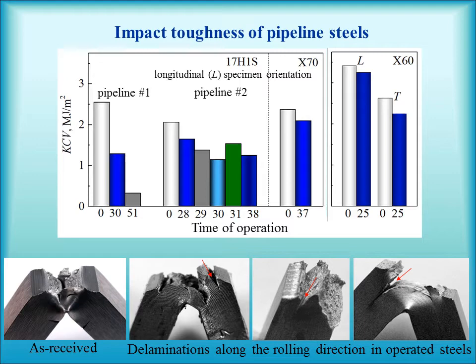It is known that the main characteristic for assessment of pipe steel resistance to brittle fracture is impact toughness. And this parameter decreases with operation time for all tested steels. It also depends noticeably on specimen orientation, as illustrated for the steel X60. Fracture of transverse specimens realizes by detachment along structural elements of the texture and therefore requires less energy consumption. In the case of longitudinal specimens, the fracture plane intersects fibers of the texture, so the fracture path deviates, as shown on the bottom pictures.